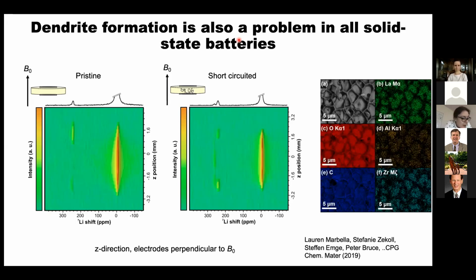Sadly, I talked about solid state batteries as being maybe a solution to the safety issues in terms of getting rid of the electrolytes, but this is an example of lithium magnetic resonance imaging of LLZO, lithium lanthanum zirconate pellets, one of the most stable materials against lithium metal. But you can see that even lithium metal is able to force its way around these large LLZO particles. This is a cross section SEM of a short-circuited pellet. You can see the lithium metal, and by the EDAX you can see it's where everything else isn't. And then by NMR or MRI, you can see the lithium that's going through the pellet.